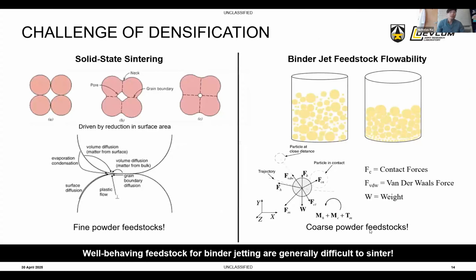The problem is that generally, because it's a dry powder process, you have two competing mechanisms, right? You want something that's really flowable, so the material packs really well in your powder bed by itself, and it will flow out of that hopper during printing. So you want pretty coarse powder feedstocks for good prints. On the other hand,